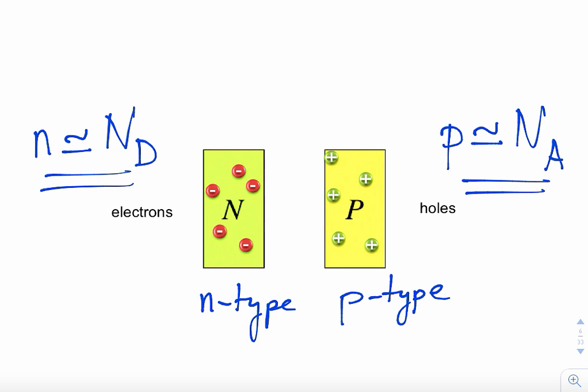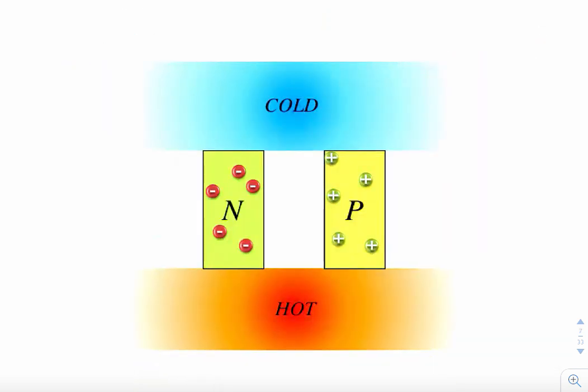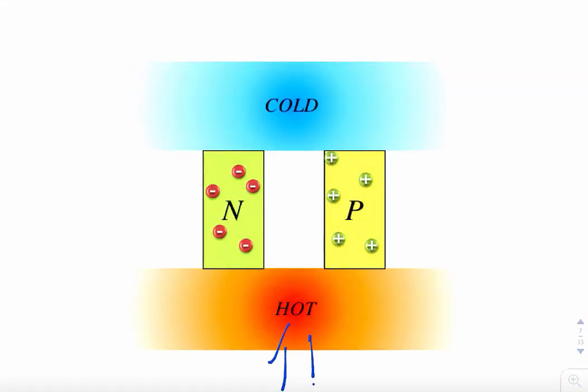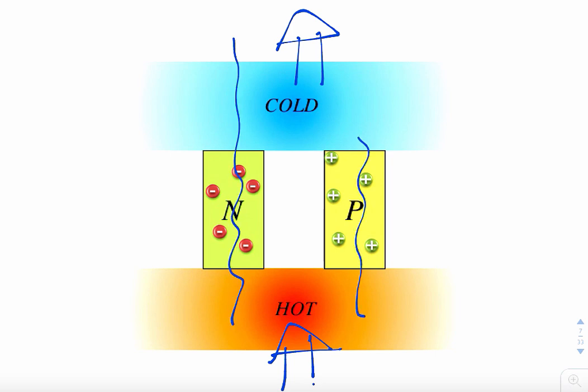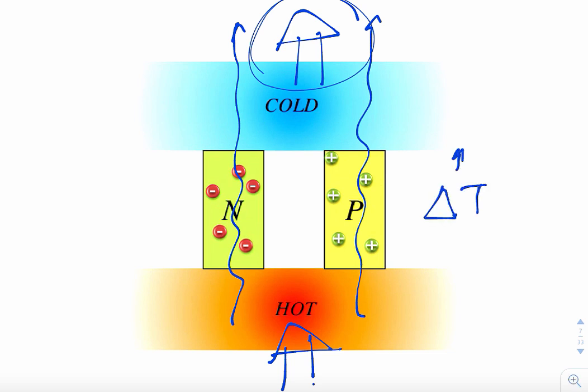In this example I have an n-type and p-type semiconductor sitting next to each other. I take these two and sandwich them between two plates. One plate is hot, the other is cold because I have a heat source providing heat from the bottom and heat is rejected from the top. There's continuous flow of heat through both legs, and because I'm able to reject the heat efficiently, this device does not reach thermal equilibrium. Delta T between the two ends is maintained, because thermal equilibrium means everything is at the same temperature.